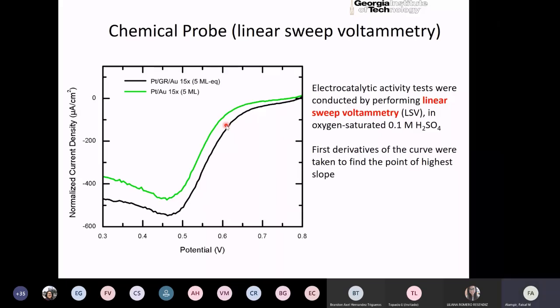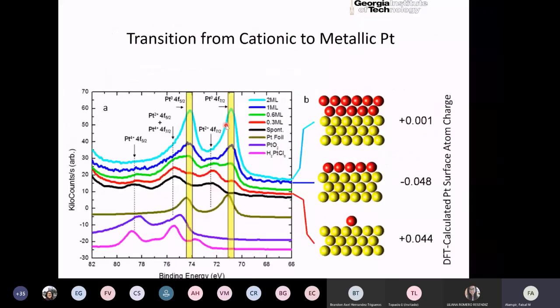One thing we noticed in our early study was that as a function of the thickness of the catalyst, we can control the chemical state of the platinum. This is a little bit busy, so let me spend a minute explaining what we are looking at. This stack of plots is for X-ray photoelectron spectroscopy, XPS. And I presume that you've heard of this technique, or maybe many of you have even used it.